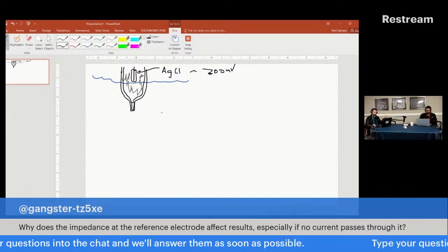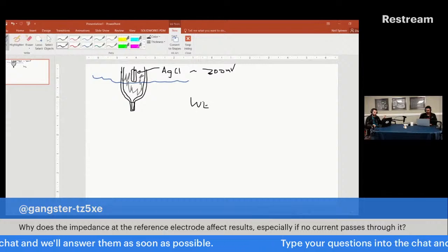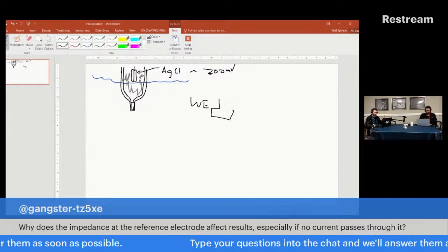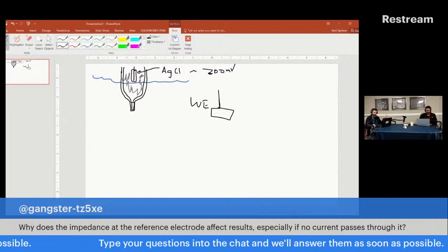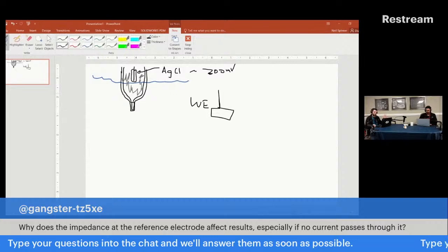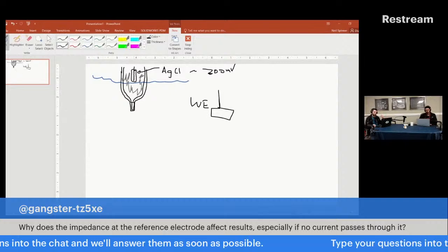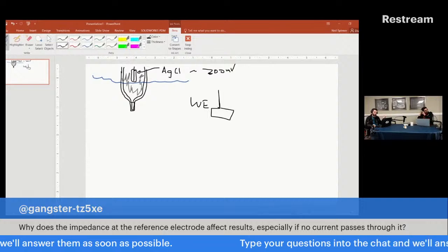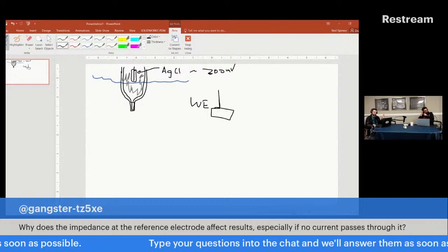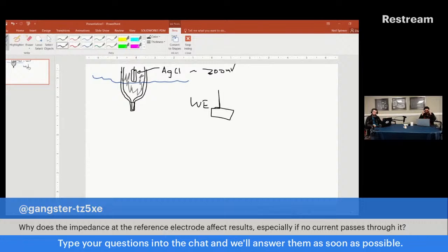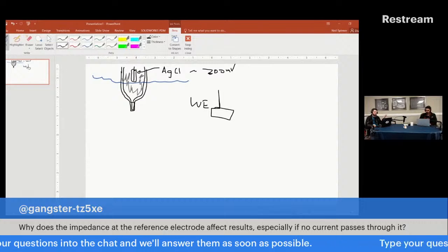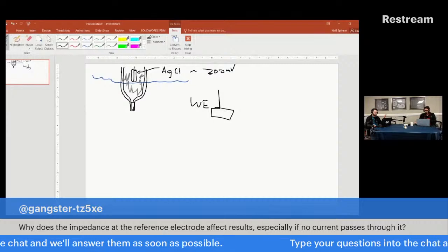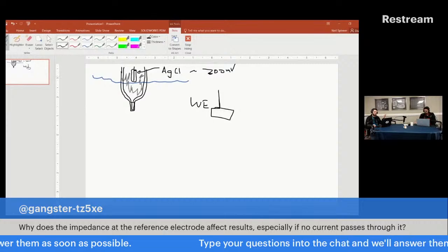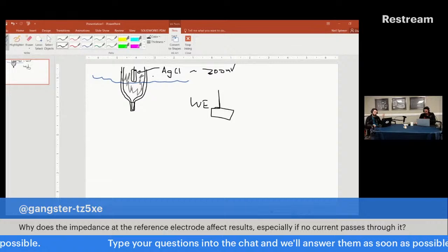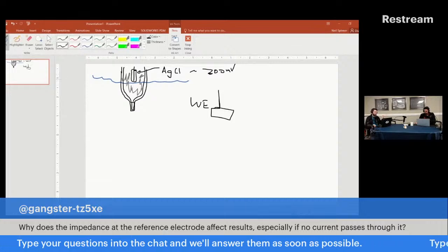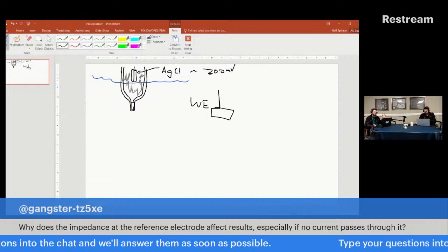Right? Somewhere over here is our working electrode. We have whatever our working electrode is, some platinum foil, some RDE, whatever it is. There has to be connection ionically between the reference electrode and the working electrode. But we contain the reference electrode usually in a tube, so that it has a nice stable potential, because the potential of this AgCl is determined by the concentration of chloride ions. And usually we do 3-4 molar KCl, something like that. Okay. So that's why we have this.